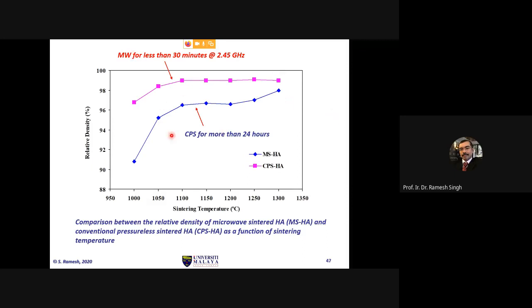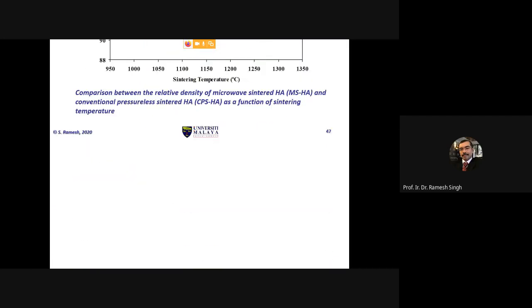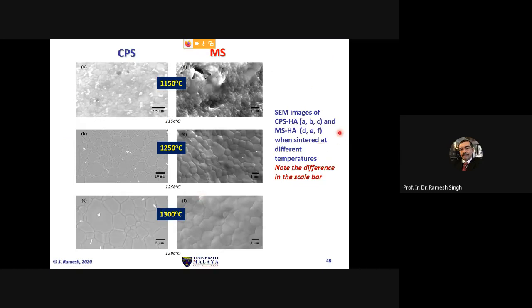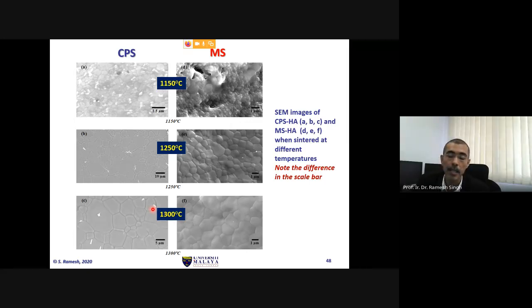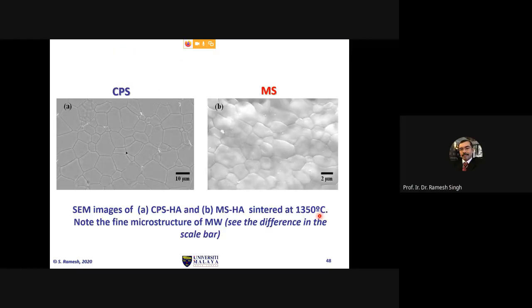So no worries about the graph. What it simply shows is that microwave processing is faster, right? In less than 30 minutes, you get very high density in comparison with conventional processing, which takes typically 24 hours. So this is all part of R&D. We look at the microstructure, we engineer the microstructure, we try to make it as fine as possible into nanoscopic range so that it can give very strong material, able to sustain high loading conditions and so on. We look at microstructure and whatnot, right?